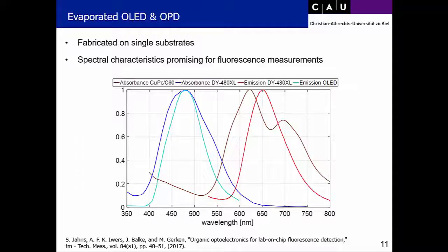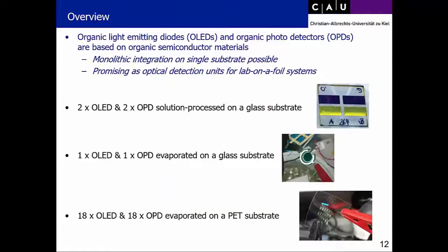So it matched quite well, but not well enough for fluorescence measurements, because we do have some absorption in this area here. So we did do fluorescence measurements and also published that in this paper down here, demonstrating that this also does not work yet, because we have too much background and we need to suppress more of the background. So we went on and did a third round, and that's what our current status is. And the third round now is using a PET substrate and fabricating a matrix.